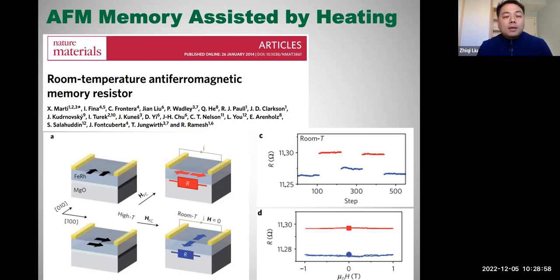of the antiferromagnetic material is different. They have a so-called anisotropic magnetoresistance effect, which is quite similar to the AMR effect in ferromagnets. But somehow, this effect is very small, around only 0.1%. Anyway, it's a first-time demonstration of a room temperature AFM memory. This already is a big breakthrough.